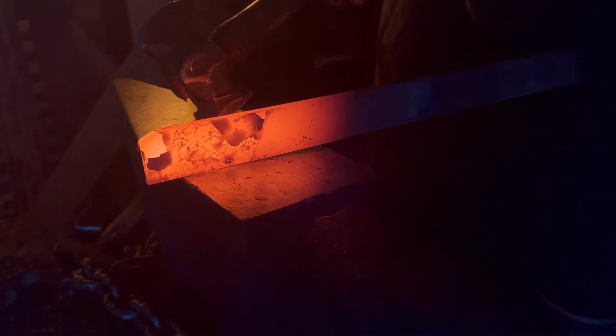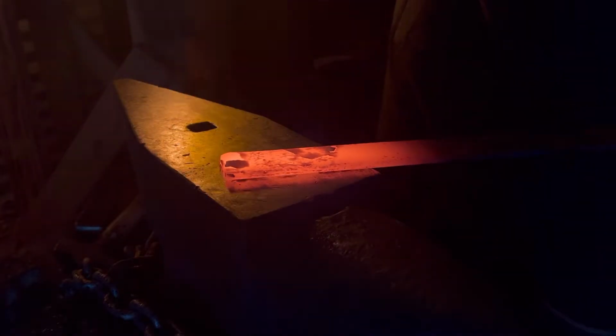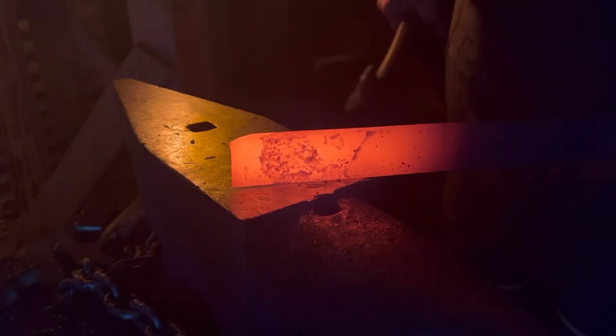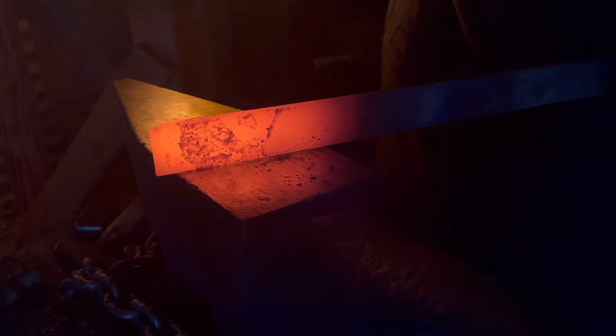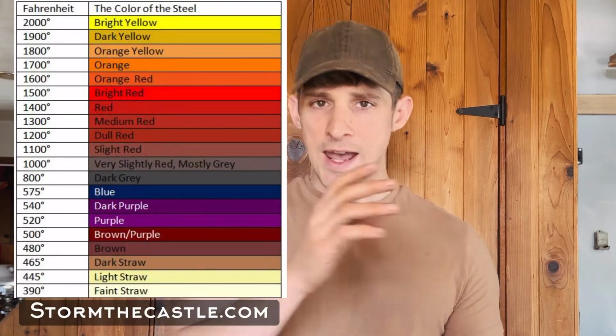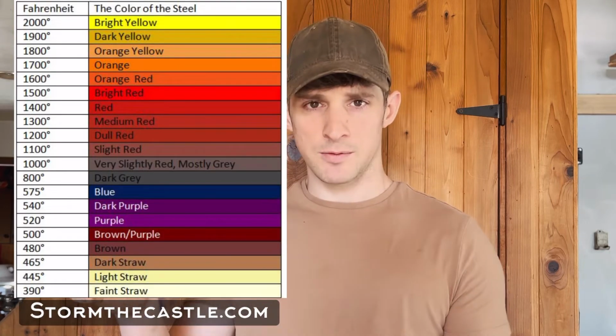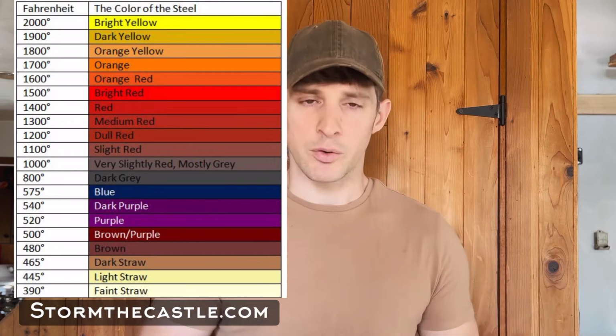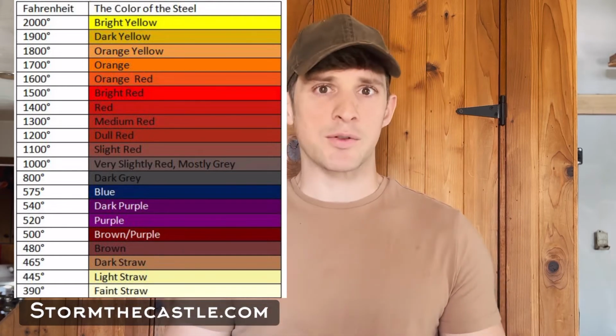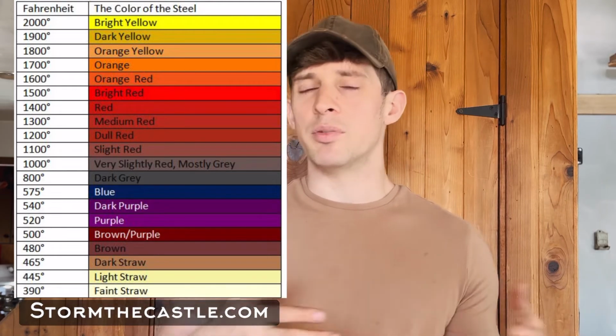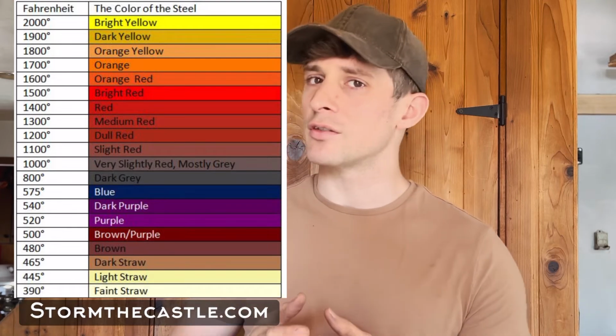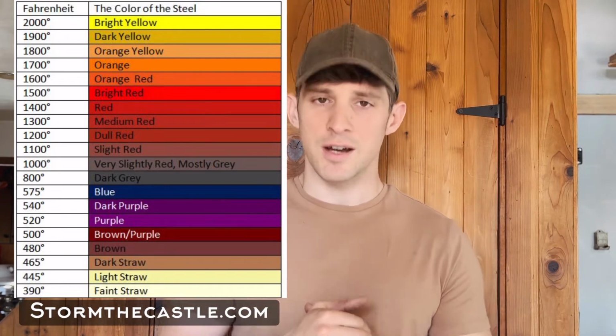Conversely, if you work your steel too cold, you will cause stress fractures all the way through that thing. Once your steel starts to drop temperature and it starts to look red or cooler, you need to put it back in the forge and not work it cold. Never, ever hammer on cold steel. Cold steel is relative, of course, because 1,000 degrees sounds like it's really hot. But for forging steel, 1,000 degrees is not hot enough.